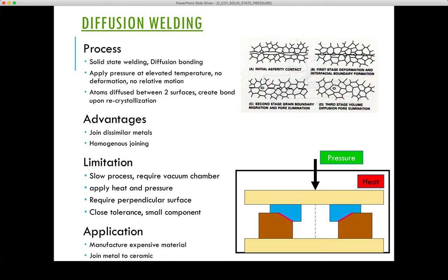How does the diffusion welding process progress? When two surfaces are in close contact, sufficient diffusion strength requires intimate contact. Surface roughness creates small contact points called asperities. An initial asperity contact is created first. To achieve sufficient diffusion and create a weld, surface preparation techniques — typically combining metal machining or grinding with chemical etching — are required to create very smooth surfaces and remove most oxides or contaminants.